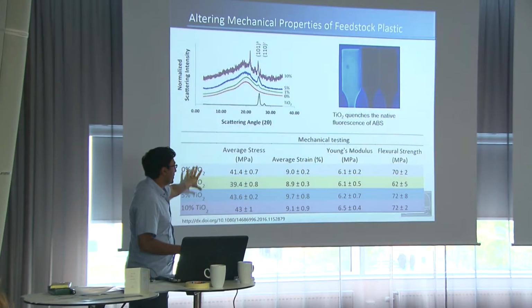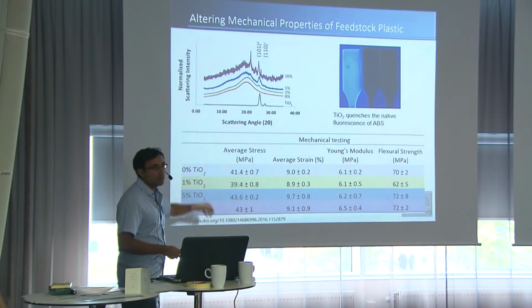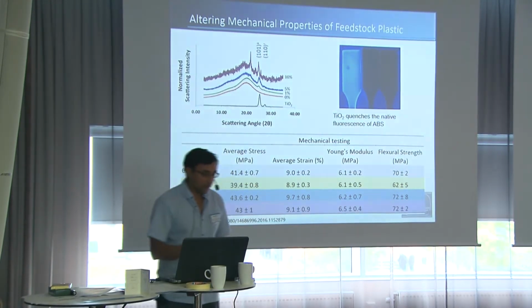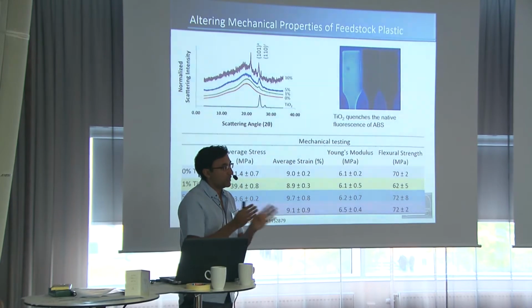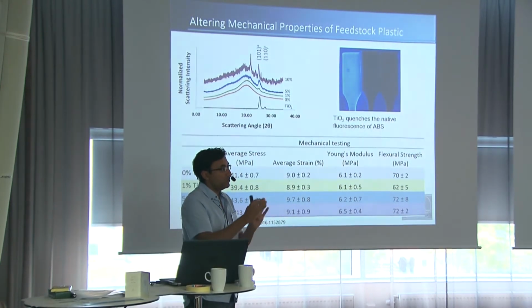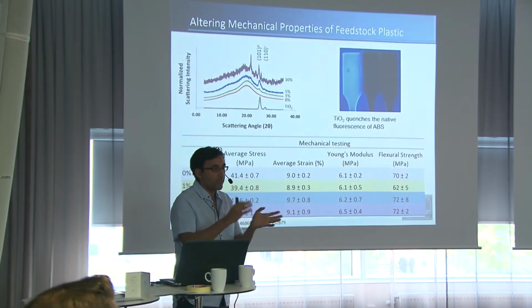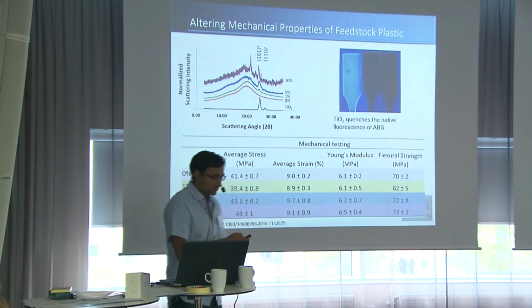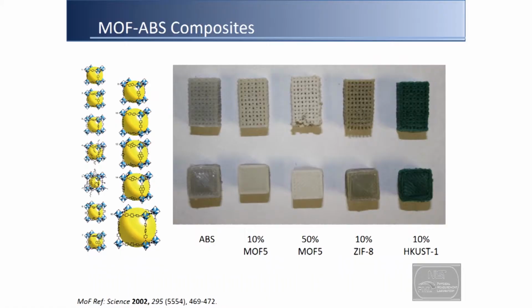More importantly, the mechanical properties: it sort of strengthens up and then gets weaker at higher loading factors. And when you look at the IR spectra, that's because the TiO2 nanoparticles start to decompose or break down the polymer backbone. So this was an encouraging result. So we moved on to gas storage materials.